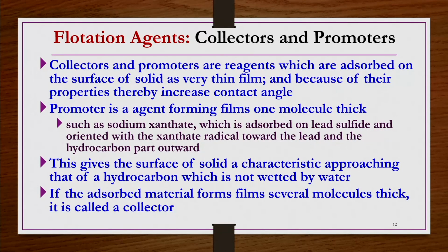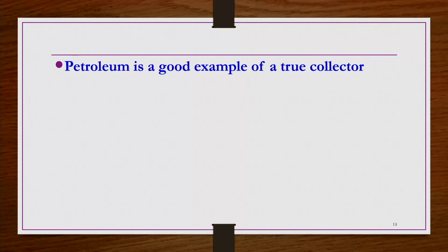If the adsorbed material forms films several molecules thick, it is called a collector. In general, petroleum is a good example of a true collector, but sometimes what happens, this forms a very greasy froth, and removing that greasy collector after the separation of the solids is again painful. So, one should be careful about the amount of petroleum added as a collector, so as to improve the floatability.